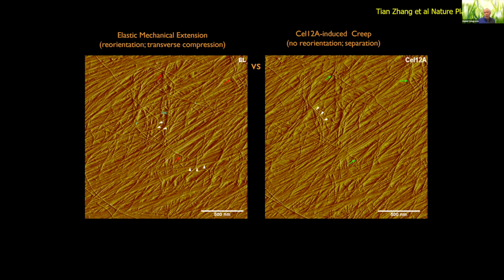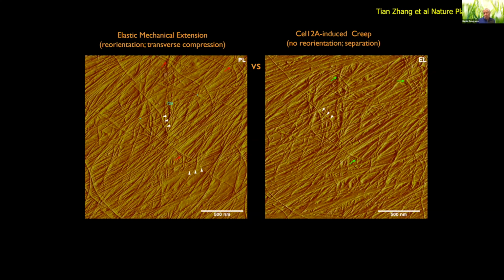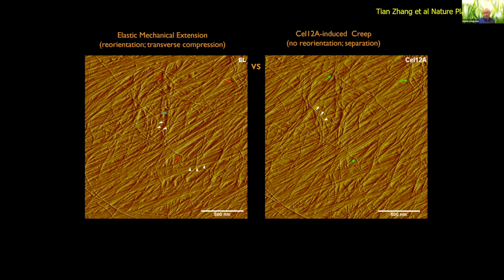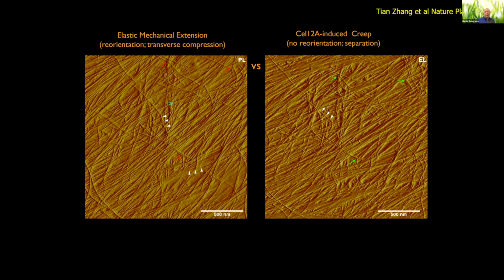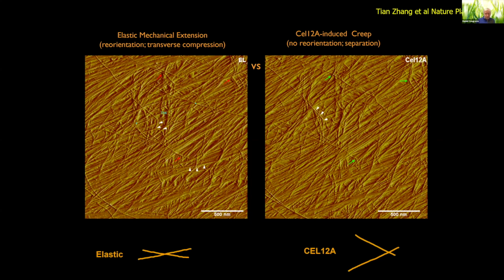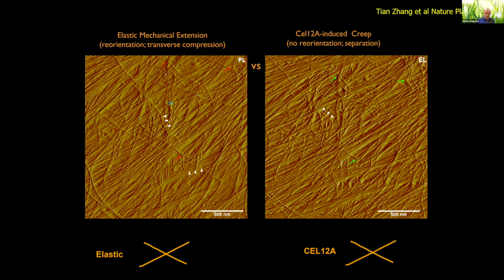We can stretch the cell wall under the AFM, and with a bit of finesse, we can see how the microfibrils are changing their organization, their structure, how they change within the cell wall as we're stretching it elastically, and that's shown in this image on the left. Or we can also make the wall undergo long-term extension, which we call creep, and study how the cellulose microfibrils change in that condition. It takes some time to study these things to see what's going on. The point is that the behaviors of the cell wall microfibrils are remarkably different under elastic, reversible extension versus the kind of long-term irreversible extension that occurs during growth, for example.